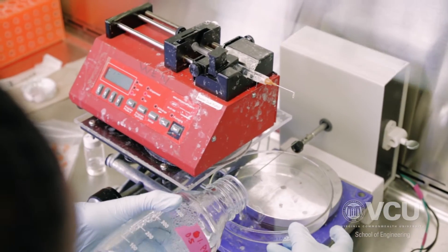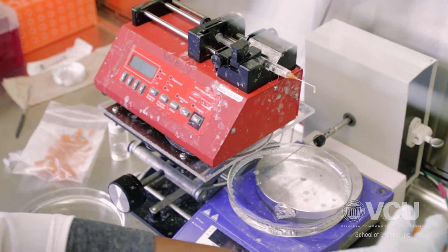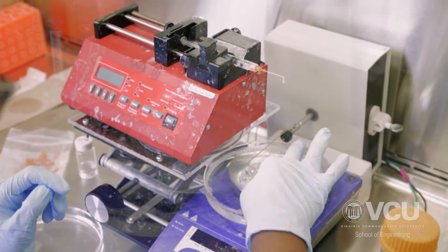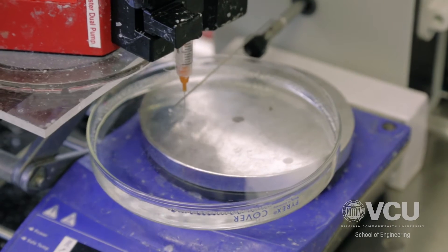I am using tiny beads called microbeads — microcarriers — and I'm using those for stem cell culture. I fabricate the beads here with a polymer, polystyrene, and then I either coat them or not coat them in order to enhance attachment of the stem cells. I then use those for cell culture and use imaging to see not only the topography of the beads but also any attachment on the beads after the cell culture is over.